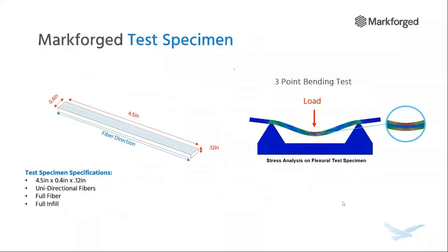And again, that's so that all the fibers are placed in tension, especially on the bottom there. The fibers on the bottom are placed in tension under that load that would be in the middle. And so these fibers are unidirectional, and it was completely filled with fiber, and it had full infill. So it is really optimized to do well in this test. And that's why it was able to outperform aluminum, because we used the best strength properties of the carbon fiber in order to maximize the performance.